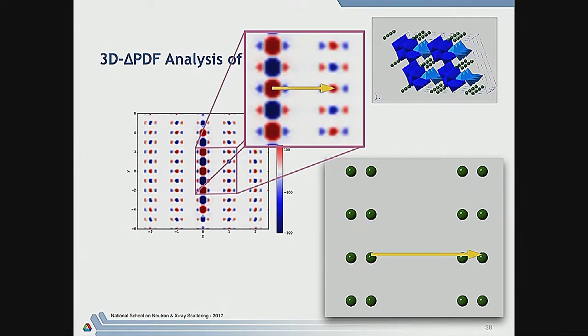But the other two are blue, so it means this one will not be, okay? And similarly, if this is occupied, this will be occupied, but not that one, because these things are blue. So we've already seen then that not only are there correlations within the ladders, but there are correlations between the ladders. And actually, without doing any modeling, you can basically say that is what the structure of the sodium ions is. There's a zigzag